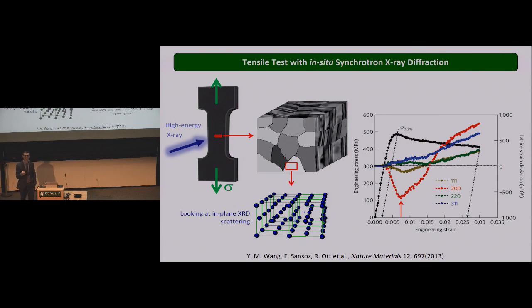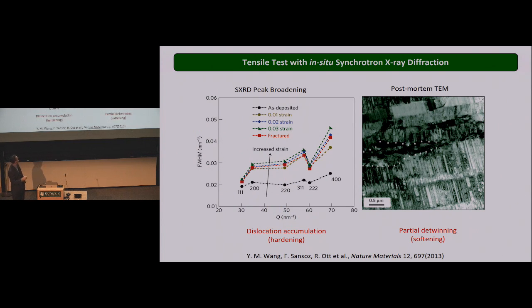What that suggests is that there is more than one mechanism in competition in this problem. It's not just pure dislocation nucleation. Something else is happening that explains this change in the X-ray diffraction. Another thing we observe is the width of the peak in the X-ray diffraction. Typically that width corresponds to any internal strain or accumulation of dislocations you have. In this case, we find a significant increase in the internal strain in the film. That means that some dislocations are accumulated. And that's totally different from what the simulation predicted before. Simulation predicted no accumulation. So something is wrong here. That's how we started this study.